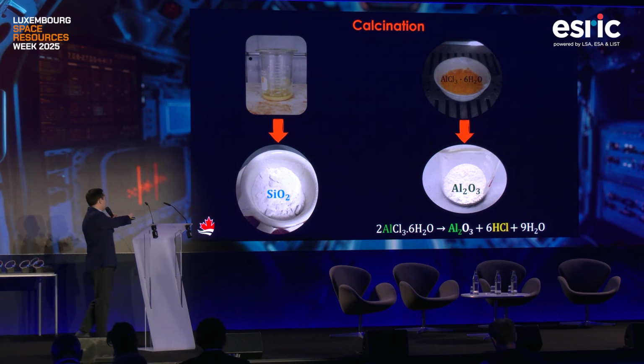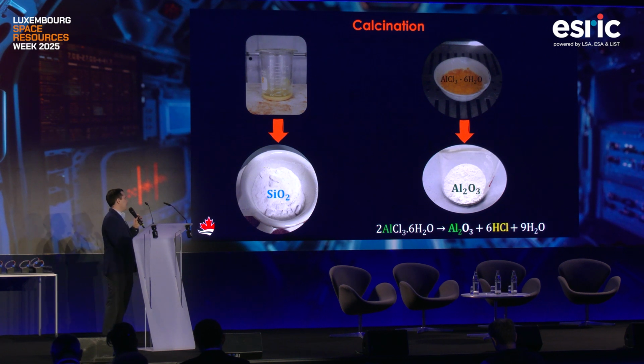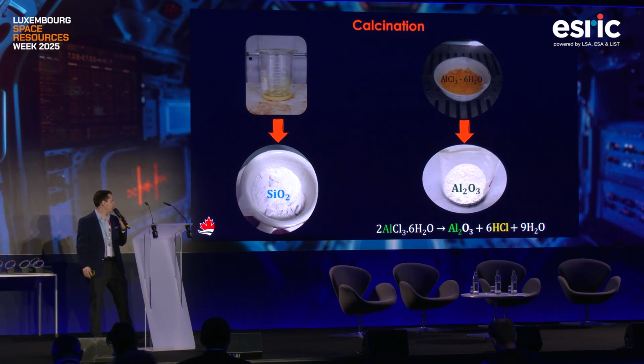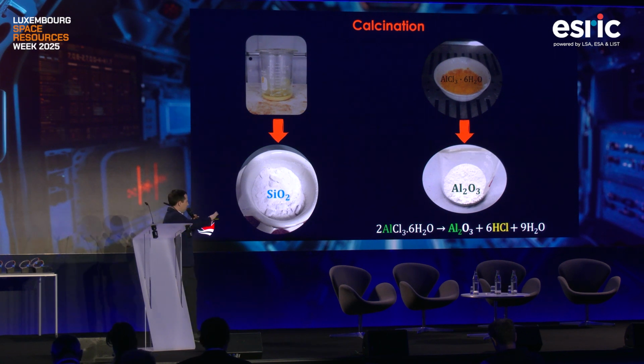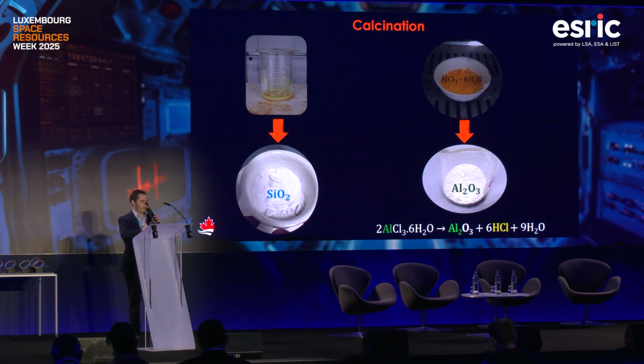And as you can see, we were able to produce silica, that's on the left side. And then aluminum chloride hexahydrate, it's a bit of a different process. You can see that there's a reaction at the bottom. That's because aluminum chloride hexahydrate dissociates at high temperatures. So if you dissociate it, you're going to produce aluminum oxides, and then you're going to get HCl and water as byproducts. So the main idea of this part of the process is that we can recycle the HCl.